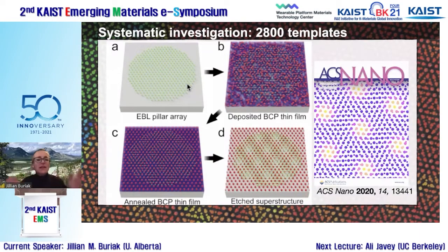pattern, the hexagonal dots. Instead of using the block copolymer to do it, we used e-beam, because then on a single chip, you can make the spacing 10 nanometers, 12 nanometers, 14 nanometers, all the way up to 80 nanometers. And then you can do the block copolymer self-assembly on that chip, so you're doing it all under the same conditions. You can then etch that and analyze these. And so he did 2,800 templates in order to generate some data from which we could do some sort of machine learning analysis.